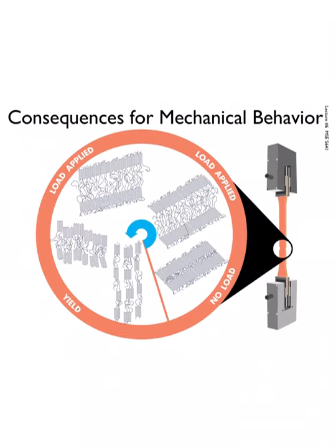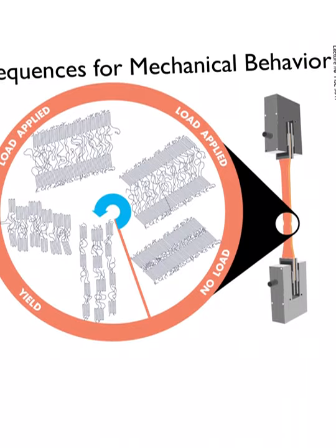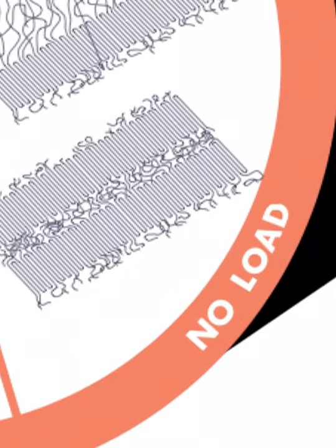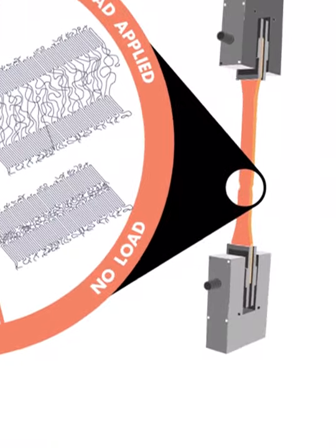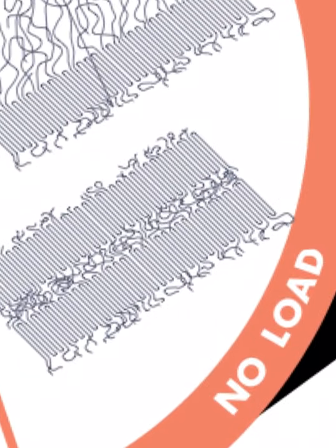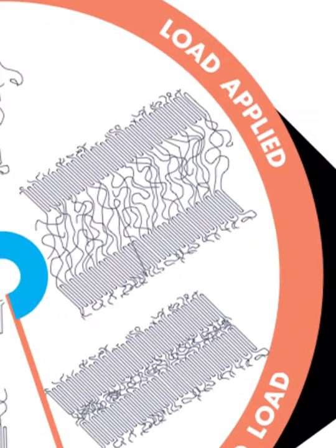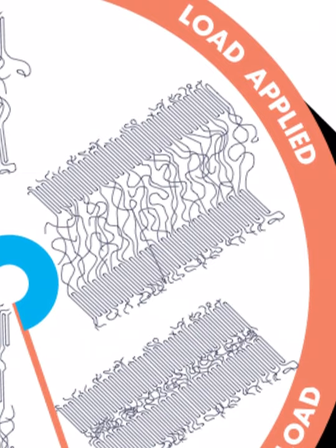All right, and so putting all this together, we can start to think about a mechanical view of what happens when we deform these polymers. And this is something we'll come back to. I call it the clock diagram. You'll get sick of hearing about this. You start out with a semicrystalline plastic under no load. Using your tensile frame, you apply tensile load to it, and that load, as it's applied, is not going to so much deform the crystalline part, because remember they're little rocks, quote unquote, but the amorphous part, which has no structure, is the first thing that deforms.